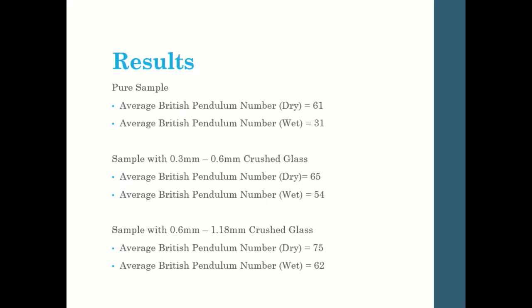So I'm seeing how much that number varies, wet versus dry. I saw that the number is significantly reduced. However, for the crushed glass with 0.3 to 0.6 millimeters, you see that the number did in fact drop when wet. However, it's still greater than that of the pure sample. And of course, the bigger size fraction had a greater value as well.